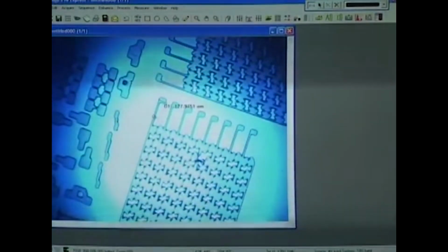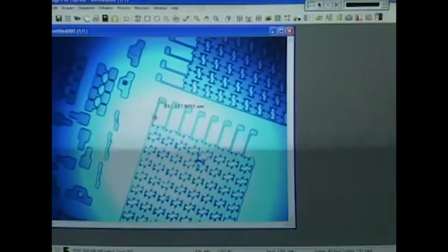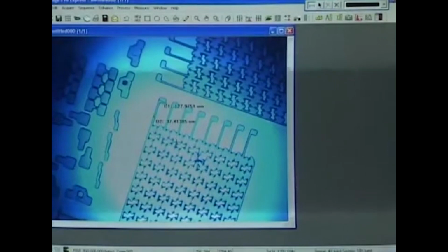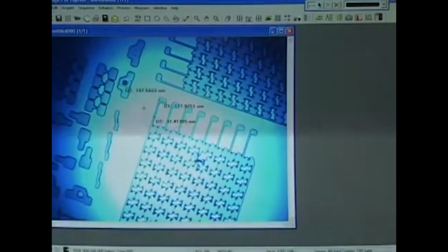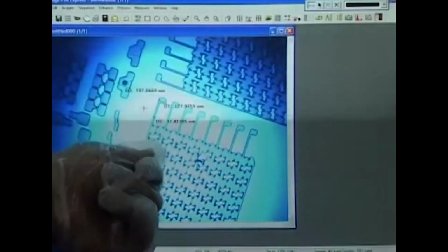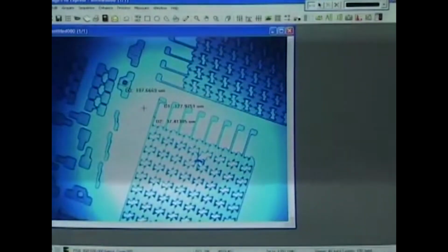So, let us say we want to connect these 2 points here on this small piece here. This is corresponding to about 37 microns. So, essentially you can measure, say, from here to here in this particular figure, this corresponds to about 187 microns. So, you can very accurately and precisely measure the size of what has been generated, and mind you, this 37 microns is only 1/3 the human hair dimension. So, it is a real small entity to be seen with normal eyes, but this powerful imaging system or modality that we have enables us to see and measure what we have done.